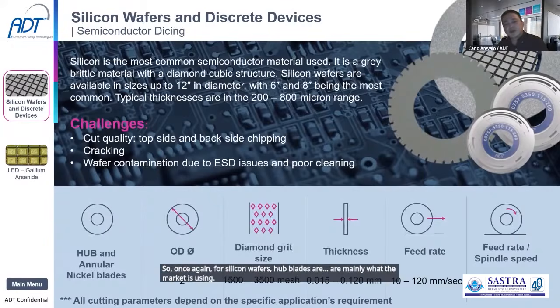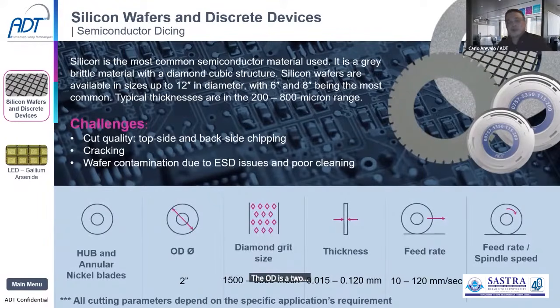The OD is at 2 inches. Grit size is from 1500 to 3500 mesh. Thickness is 15 micron to as thick as 120 micron. Feed rate can be 10 to 120, but this can still go up to 150 or even 180 mm per second. Spindle speed is dependent on the blade size.